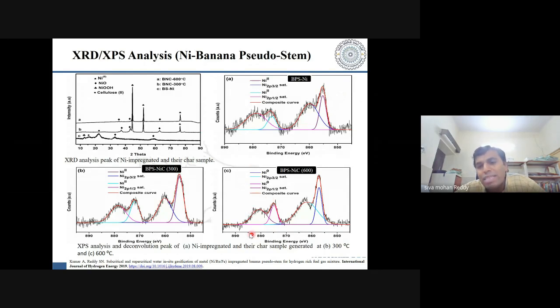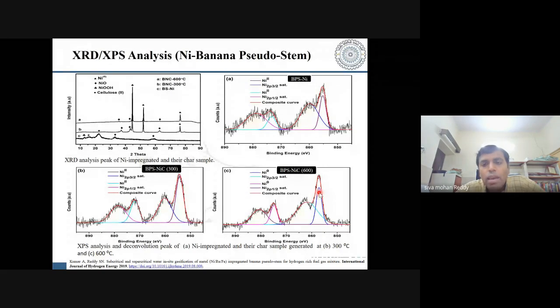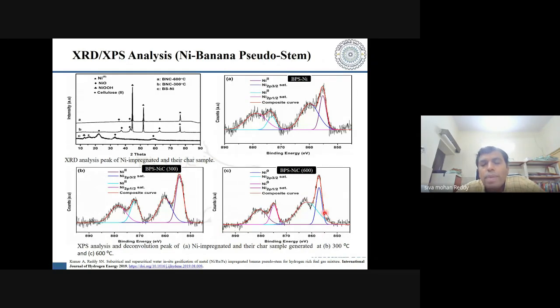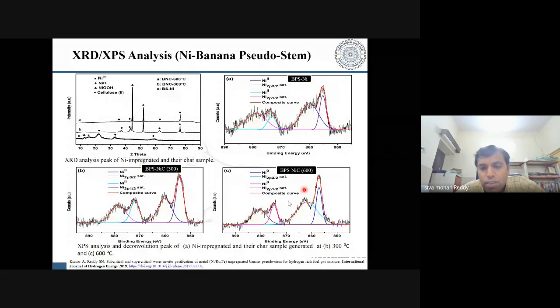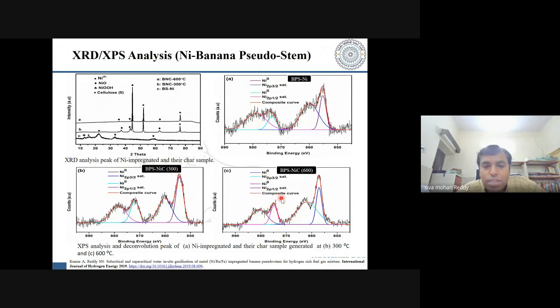Now, as soon as you take it to 600 degrees centigrade, you have a sharp intense peak at around 857, which corresponds to the binding energy of your active nickel nanometal. We have already confirmed from the TEM analysis that nickel existed in the form of nanomaterial. So the binding energies corresponding to 857 and 874 correspond to your active nickel metal, with the corresponding satellite peaks at 2p 1/2 and 2p 3/2.